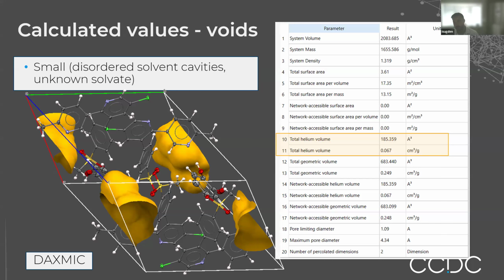But you can then start making predictions of what would fit inside that, and so this 185 cubic angstrom is about 2 acetonitrile molecules, and you can see that you can then tell that this is a solvated structure where the solvent was removed.